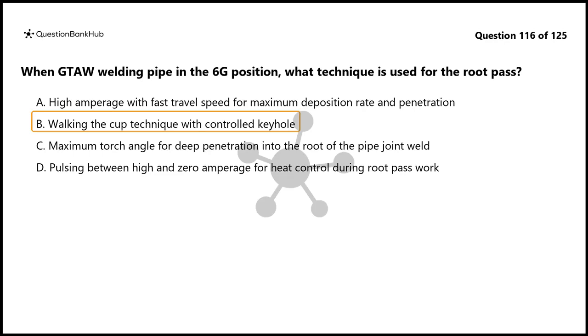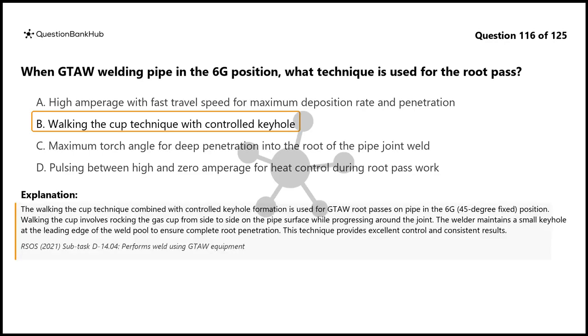The correct answer is B. Walking the cup technique with controlled keyhole. The walking the cup technique combined with controlled keyhole formation is used for GTAW root passes on pipe in the 6G, 45-degree fixed, position. Walking the cup involves rocking the gas cup from side to side on the pipe surface while progressing around the joint.